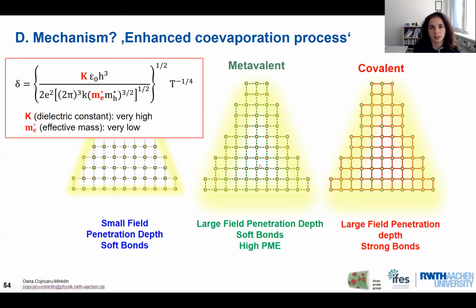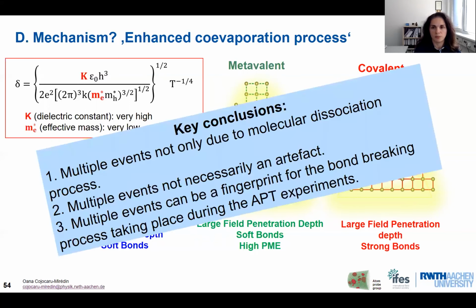And the second ingredient is that the metavalent bonding is rather soft, like metallic bonds. So these two ingredients, high penetration depth and very soft bonds, are the ones which explain the enhanced coevaporation process and explain why we get so many multiple events during the atom probe experiments.